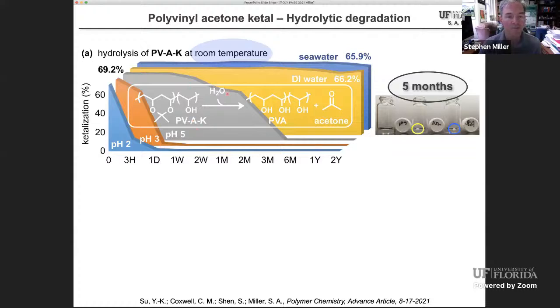At pH 5, complete hydrolysis is seen, but not until 6 months has transpired. You can see a picture here. In deionized water, we still see the little piece of plastic. In seawater, we still see the little piece of plastic. But after 5 months at pH 5, little piece of plastic is gone. Seems to be dissolved. It's turned back into water-soluble polyvinyl alcohol and acetone.